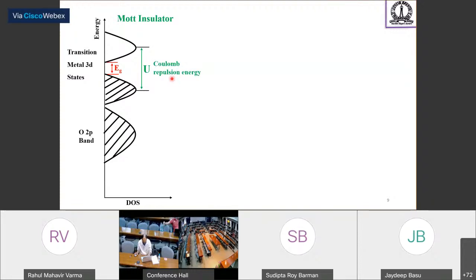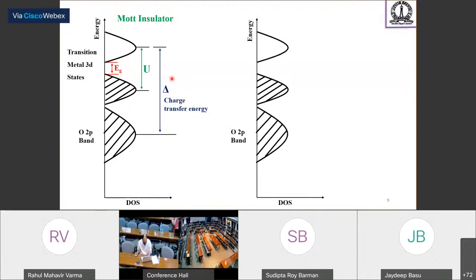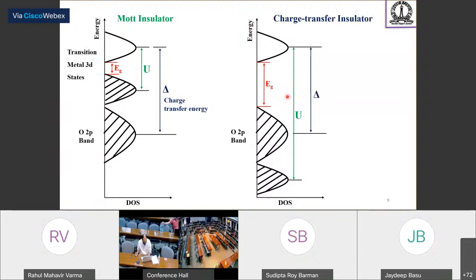This puzzle was solved by Zaanen, Sawatzky, and Allen, who introduced another kind of energy which plays an equally important role, namely charge transfer energy. If you have a system where the Coulomb energy is large, then the lowest excitation will happen from oxygen 2p to the transition metal 3d ion, and now the band gap will be given by the charge transfer energy delta. So Zaanen, Sawatzky, and Allen argued that the band gap will be determined by the smaller of these two quantities.